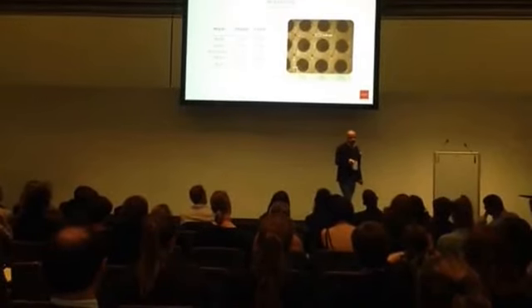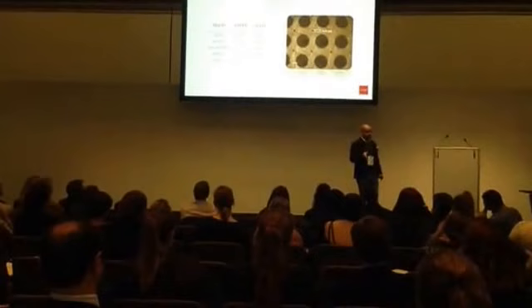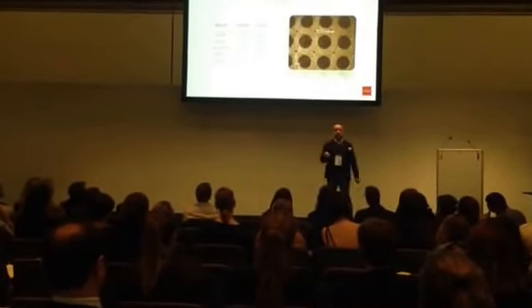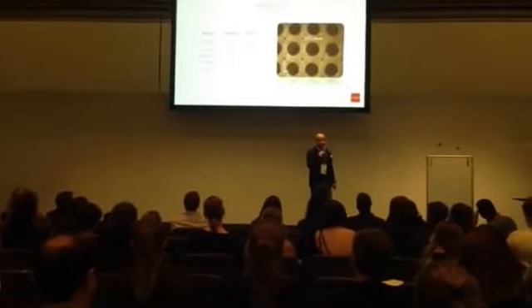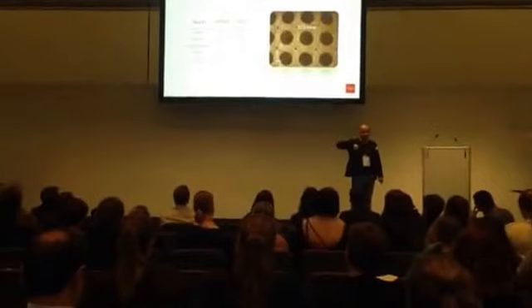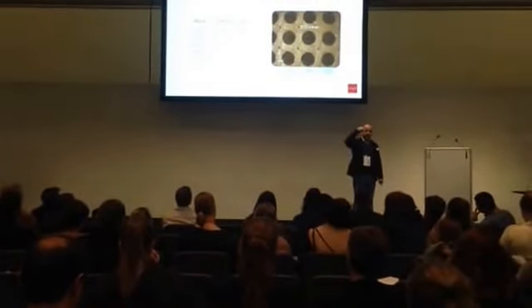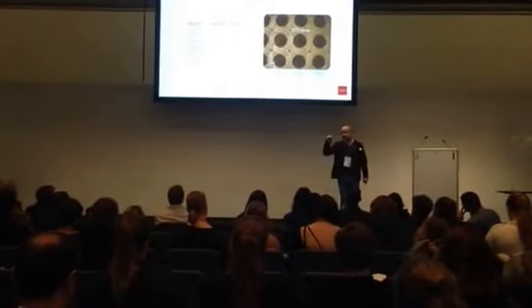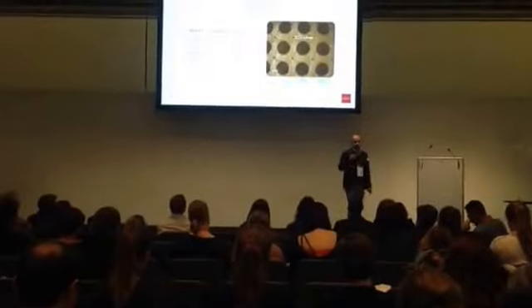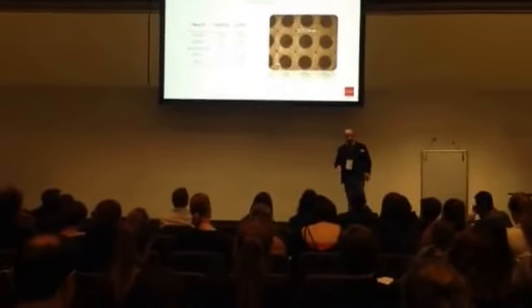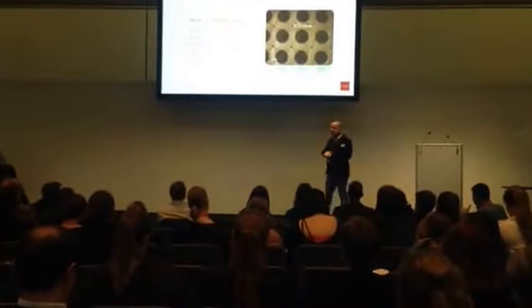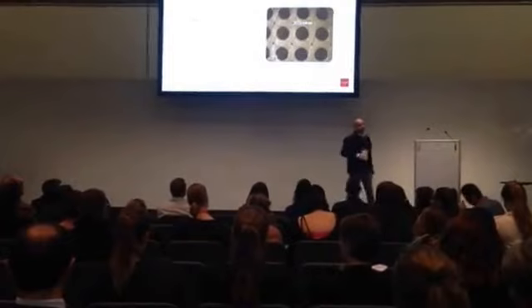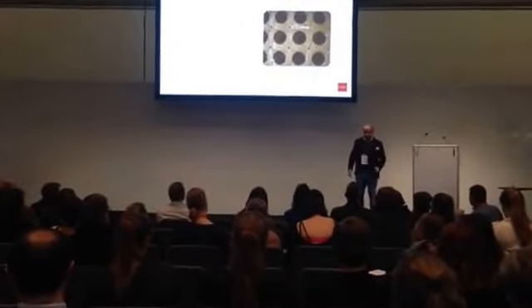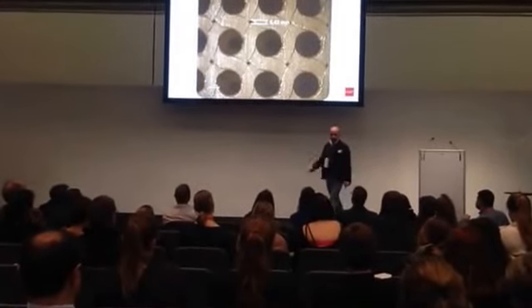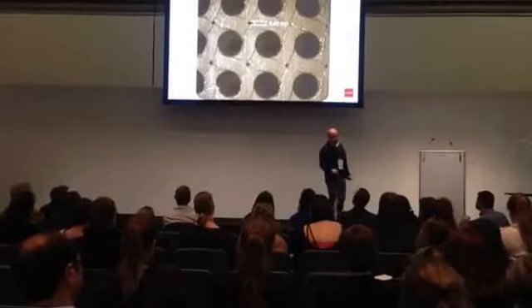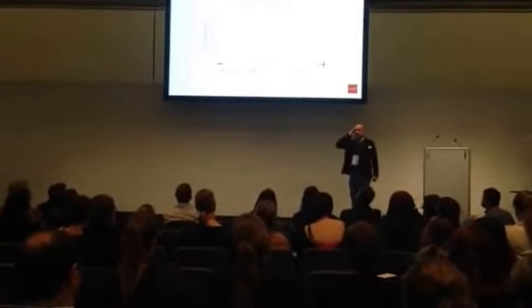Then in the case of platinum, you see that we have a much higher resolution on XY, under 70, because it's absorbing the power very well, and the melting trace is much thinner. It's like having a pencil: when you draw with a thick pencil, you are not able to do the same details as if you use a thin pencil. And platinum is like a much thinner pencil. On the Z-axis, we have a very high resolution that is up to 1200 because every layer is 20 micron. So here you can also see the kind of resolution in one ring that is possible to achieve with 3D printing.